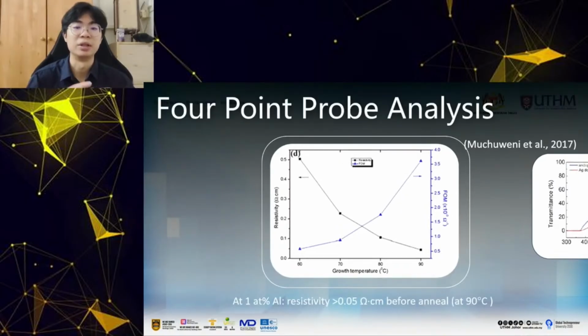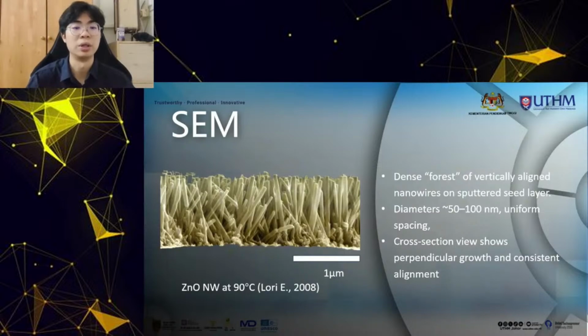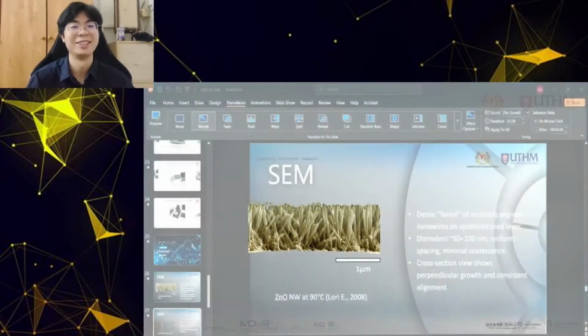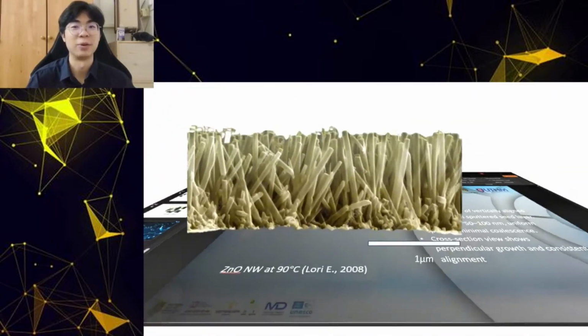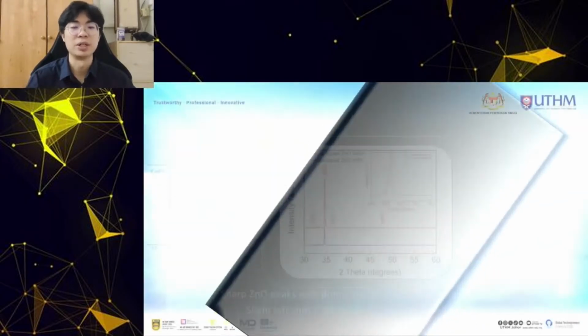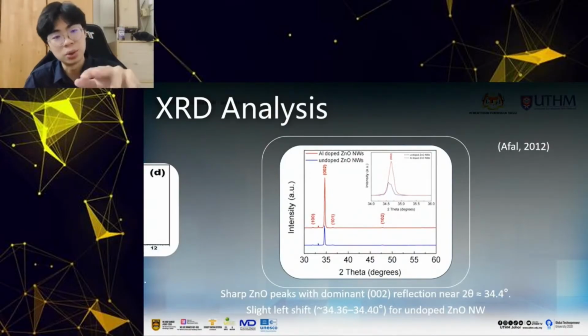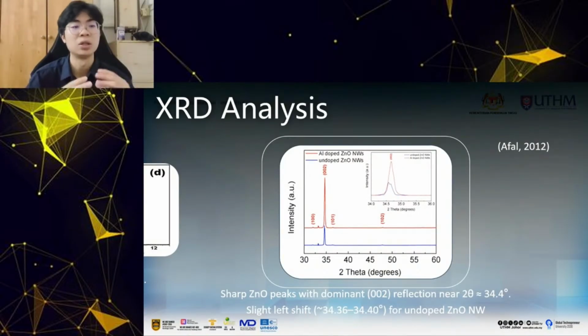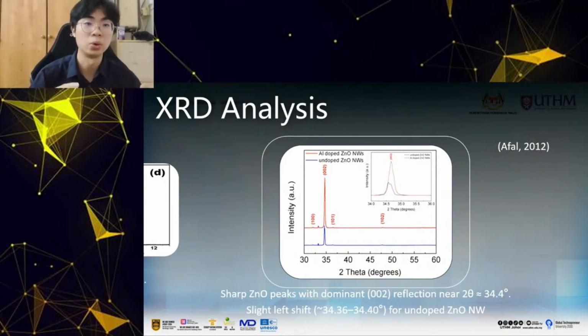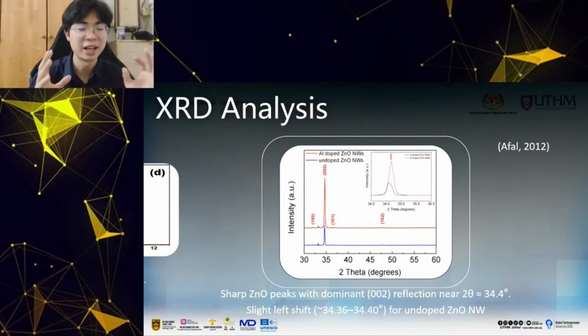So as you can see, the dense forest of vertically aligned nanowires on a seed layer with a diameter of 50 to 100 nanometers and uniform spacing, and this cross-section view shows perpendicular growth and consistent alignment. So here's a more detailed view. Okay, next for the XRD analysis: sharp zinc oxide peaks with dominant 002 reflection near 2 theta 34 degrees, and a slight shift for the doped sample. It's predicted that from 0.9 to 1.2 atomic percentage, the shift will be very slight to be observed.